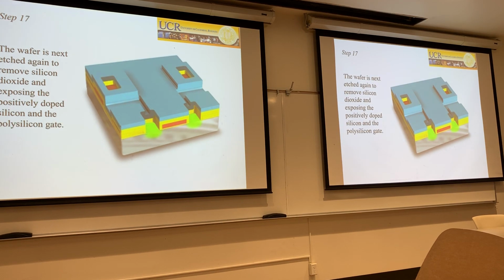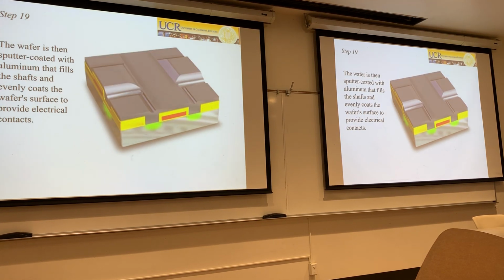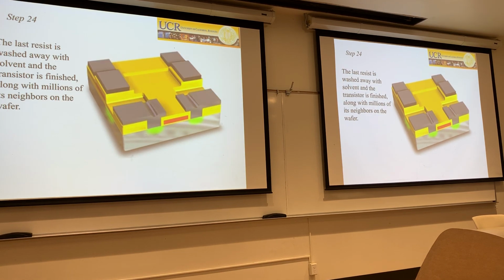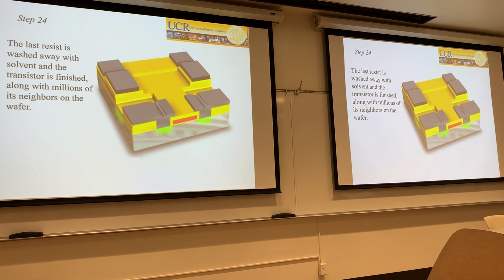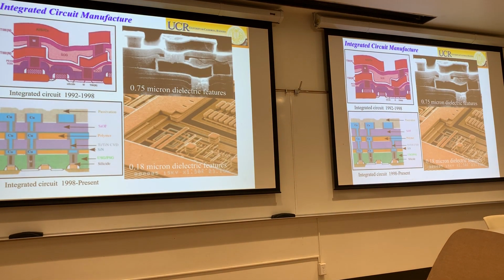Okay, and then it keeps going on and keeps going on, and you make more and more of those steps. I'm not going through any one of these steps anymore over here. At some point you will probably deposit some metal in order to wire the whole thing up. That is actually also something where my research group works on, figuring out not using a metal like aluminum or copper or platinum in there, but whether we can use metal chalcogenides as that metal. Because at 7 nanometer, that wire diameter, copper doesn't work anymore very well. And we think we know something which can work well. And so that is part of again what my research will do.